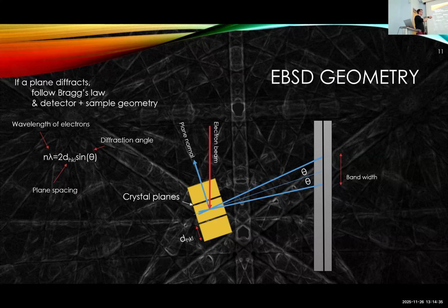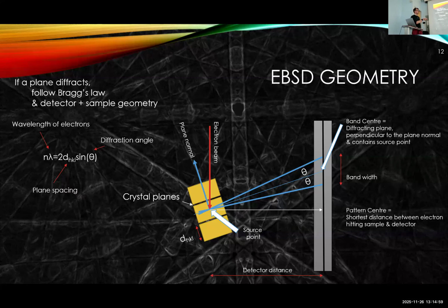So we have a bit of geometry: we have the electron beam, we have the crystal orientation, how it presents the band center, we have the plane normal running up here. And so if we know the position of the sample with respect to the screen, and we know which plane is which, we can then relate that plane to a reference orientation. Pretend I have two left hands. And that's what the computer's doing for us. And so we see that the band center is described by the diffracting plane. Effectively, it's perpendicular to the plane normal and contains the electron source point. We have the pattern center, which describes the distance of the sample from the detector and the position of the interaction volume with respect to the detector. It's a calibration bit of geometry that's important.